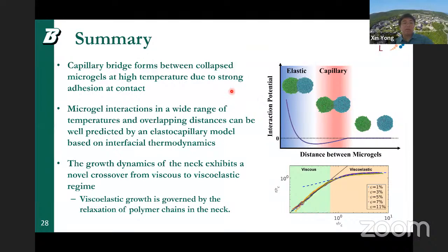And so I want to quickly summarize this so that I have time to talk a little bit about the DPD with electrostatic interactions. So basically, we're looking at how the microgels behave very differently as a function of temperature in terms of their interaction. And more importantly, when they are in the collapsed state, they exhibit capillary dominated attraction. And so we can model that very basically based on the interfacial thermodynamics, using a very simple toy model. And then we also see that the growth dynamics of the neck exhibits a novel crossover from the viscous to viscoelastic regime. And then in the long time regime, the viscoelastic growth is only governed by the polymer relaxation in the neck, which is intrinsic, which is relatively counterintuitive.